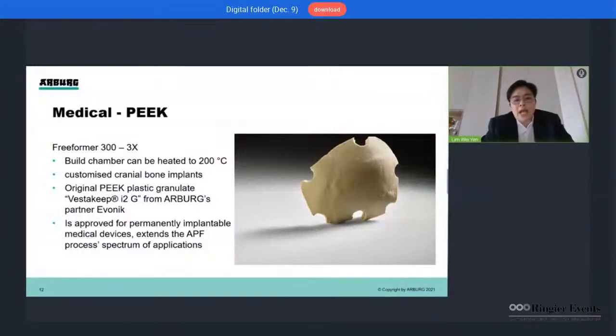This application shows the high potential of the latest achievement in further developing and adapting our AM technology for high performance materials. The Freeformer 300-3X can be equipped with a water heat exchanger, which allows us to reach a build chamber temperature of 200 degrees Celsius, and a melt temperature of 450 degrees Celsius at the nozzle. This is normally required to process high performance materials. For instance, the Ultem PEI is also an interesting material that is also presented at the exhibition.